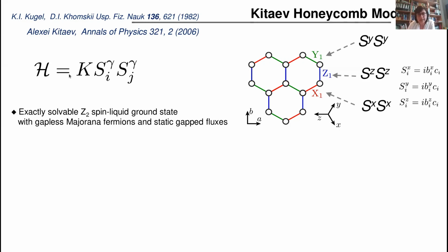So what is this Hamiltonian about? You start with a Hamiltonian on a honeycomb lattice that consists of nearest neighbor Ising interactions, but these nearest neighbor Ising interactions are bond dependent. If we situate ourselves in the center of the honeycomb lattice, the Z component of the spin of this site is going to interact with the Z component of the site on top.